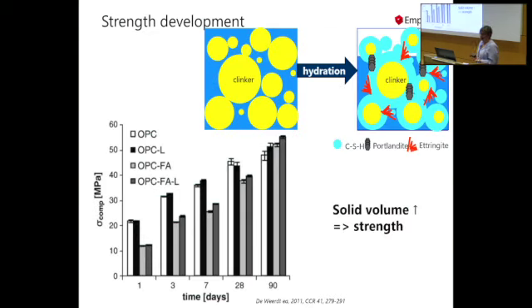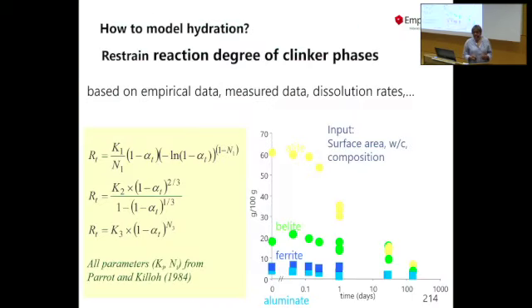And maybe because we all know when the cement hydrates, we get more and more strength, and this has to be related to the formation of more and more solid. And we also know the higher the solid volume is, or the lower the porosity, obviously, the higher our compressive strength gets. Then we said, okay, we have a restrained dissolution of our clinker.